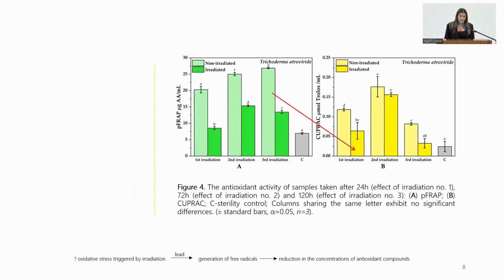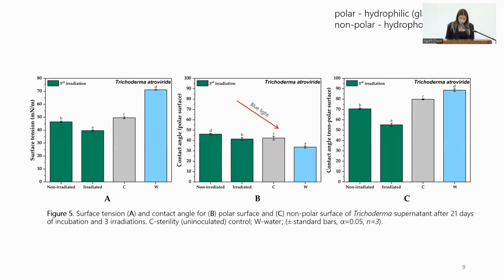The antioxidant activity also had a heterogeneous behavior. Irradiation induced a decrease in the FRAP and CUPRAC activities compared to those not exposed to the blue light. This may be a consequence of oxidative stress triggered by irradiation. This stress can lead to the generation of free radicals, ultimately leading to a reduction in the concentration of antioxidant compounds present in the sample before irradiation. More in-depth studies are needed to confirm this hypothesis.